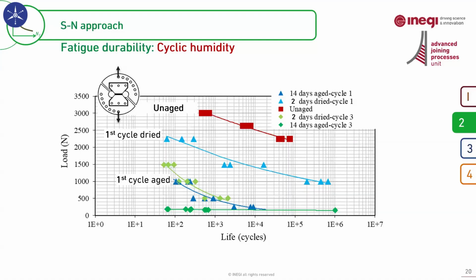And again, it means that for characterization of adhesive in terms of humidity under cyclic conditions, in case you perform a constant aging test for a joint that in practice is subjected to cyclic aging conditions, you most probably will overestimate the service life, which is dangerous and critical for design.